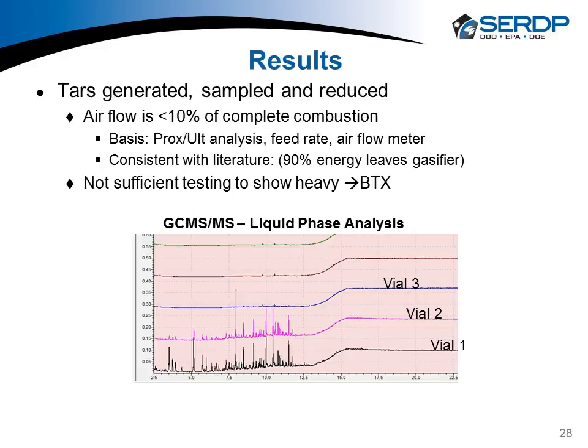But what we found was the airflow was about 10% of complete combustion. We looked at how much feed we were putting through there per day, and what the airflow reading was. We did proximate and ultimate analysis, so we know how much potential combustion energy is there. And what we found was that less than 10% of the airflow was going through for complete combustion, which is consistent with literature. And it was significantly less than 10%. It was about 9.4%. And I think the reason for that is all the extra plastic material that we had in there that was basically fractionating and leaving the gasifier.